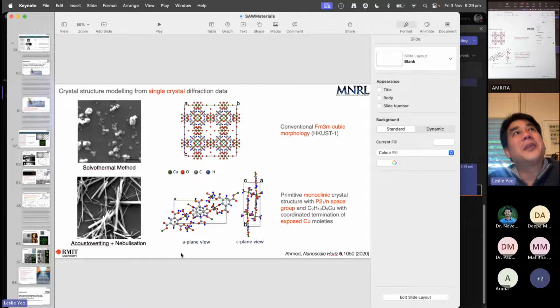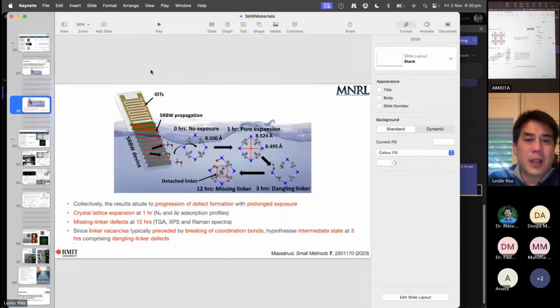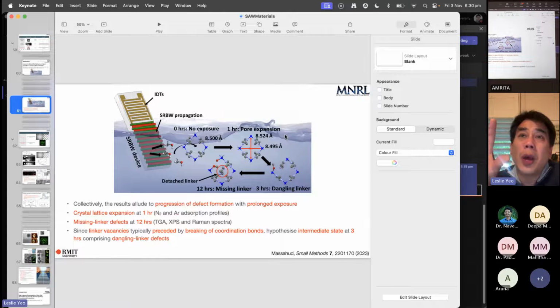Again, we've never really tried, or at least we didn't examine it too carefully. We measured it after, for example here, 1 hour, and we saw pore expansion. I don't know what happens if we waited and left it be. Would it shrink again? I guess different MOFs might behave differently. The more unstable MOFs might shrink back. In fact, MIL is known to swell, right? So maybe that's something we can look at if you're interested, to see over time whether they go back. But I guess it's more relaxation than reversibility. Once you cross that barrier, you start breaking bonds and it becomes irreversible, I think.